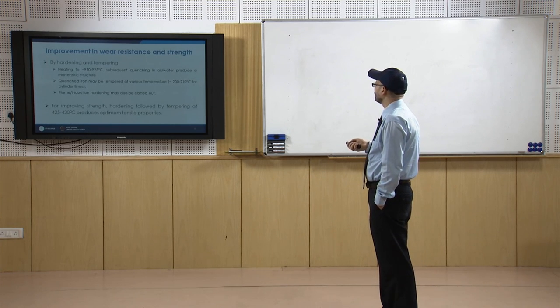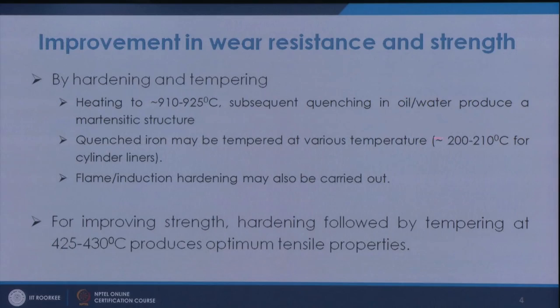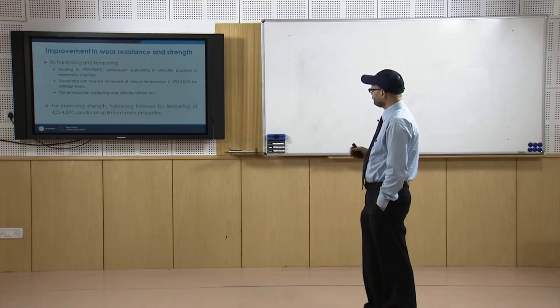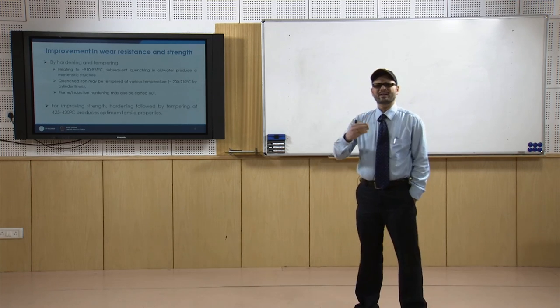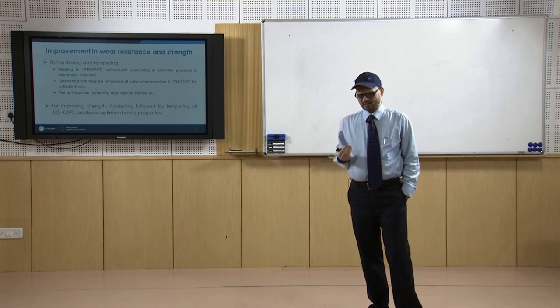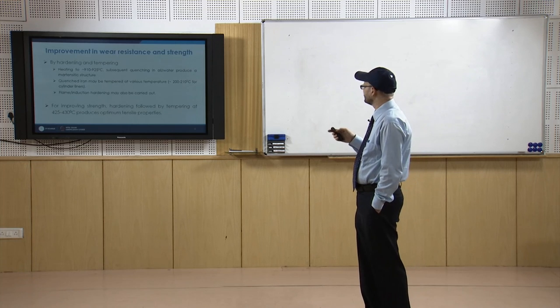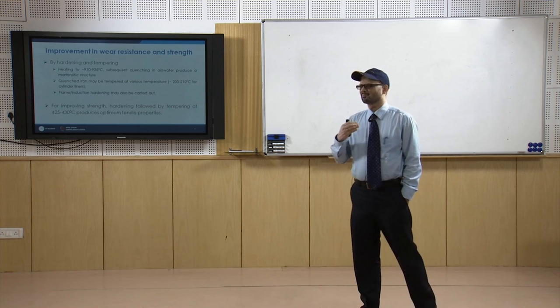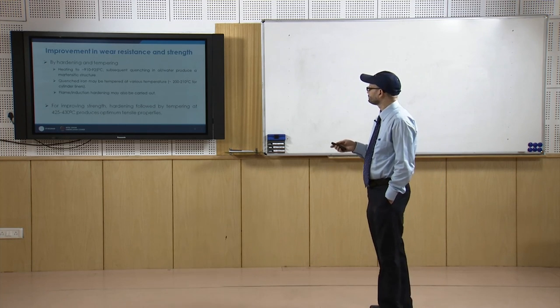Tempering will be done at various temperatures. Suppose in the case of cylinder liners, you first make it hard and then temper it at a temperature of 200 to 210 degrees centigrade for some time. That way you are giving some softness to the completely brittle phase, so that the martensite phase is tempered.